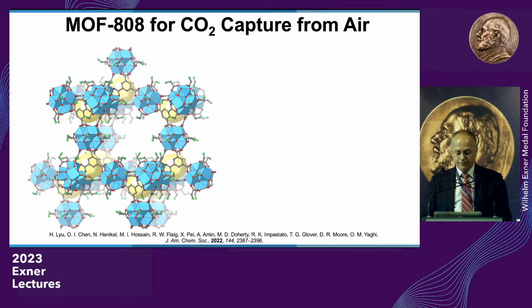Here's a MOF that is programmed by virtue of having functionalities like, in this case, glycine. Glycine has a carboxylate on one end that binds to the metal on the multimetallic unit, and on the other end it has an NH2 unit, a primary amine, chemist language. And that primary amine is ideal for capturing CO2 from air. CO2 goes to that amine unit, binds to that amine unit to make carbamate or carbamic acid, depending on how much water is being bound to the cavity. So this is something we've been working on, and that MOF we call MOF 808.